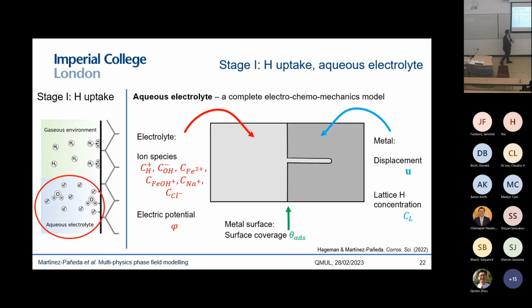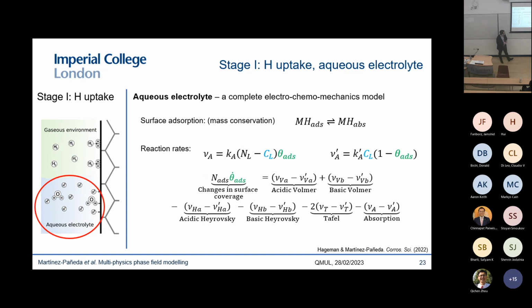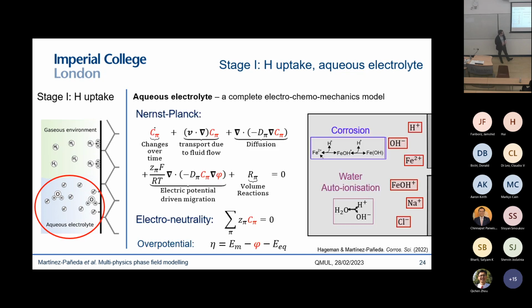So we need to solve as well the electrochemistry, we need to solve the electro-chemo-mechanical problem. So we can have a system like this one where you have effectively three domains. You have an electrolyte where you solve for as many ionic species as relevant to your problem. You also solve for the electric potential over there. Then you have an interface where you're solving for the occupancy of hydrogen atoms in the interface. And then you have a solid metal domain where you're solving the deformation problem and also for the hydrogen concentration in the bulk of the material. And I won't get into the details, but yeah, there are some equations that describe the reaction rates at the surface.